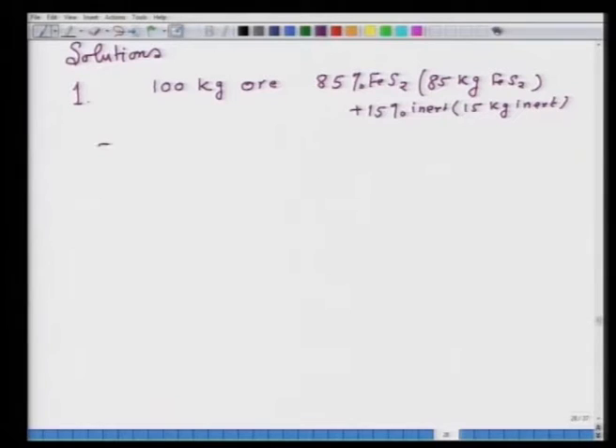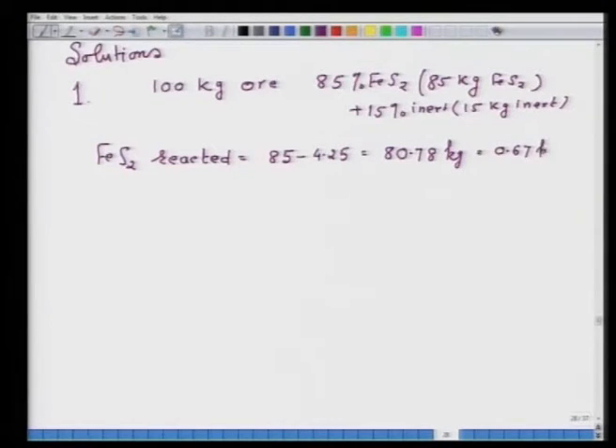So, FeS2 reacted will be equal to 85 minus 4.25, that is 80.78 kg, and that will be equal to 0.67 kg moles. Now, here I have used the atomic weights of iron and sulfur. Iron I have used 56 and sulfur I have used 32. So now straight away I can write down the equation.